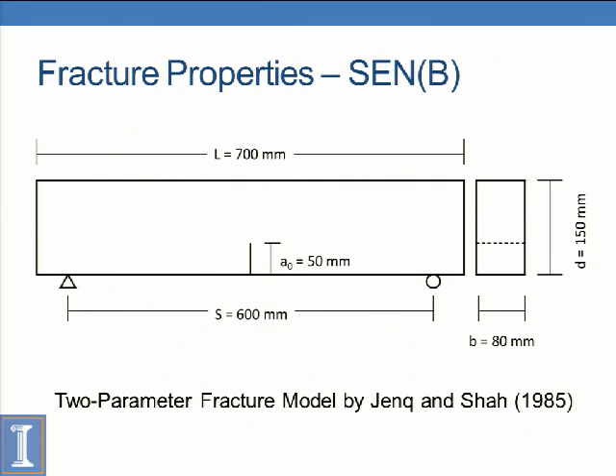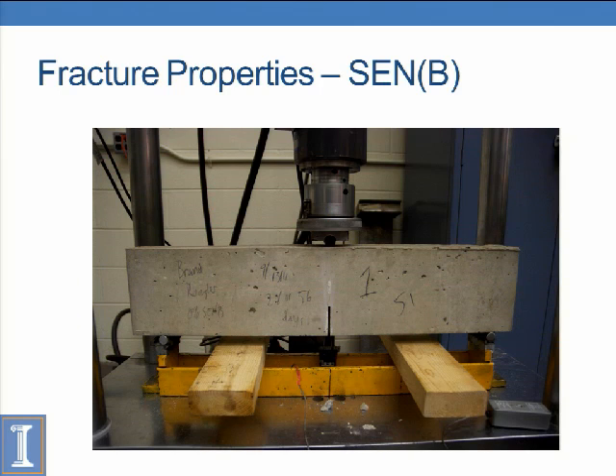Now coming to the fracture properties tests we did. We did a single-edge notched beam using the two-parameter fracture model by Jenq and Shah, which I believe is a pretty well-known test setup and study. So pretty much all it is, we have a long, thin beam. We cut a notch of 50 millimeters over the 150 millimeter depth, and then we load it from the top, and we have a clip gauge at the bottom measuring the crack mouth opening displacement.